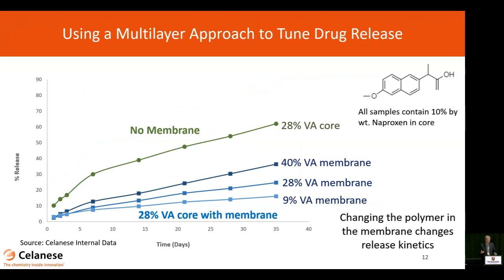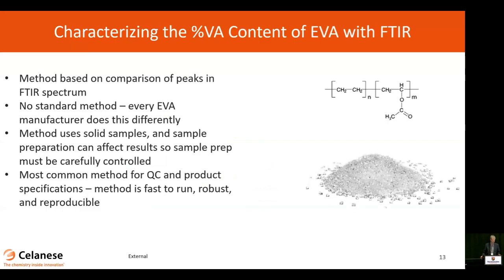Here's just another really simple example that we did in the laboratory with naproxen. Again, an easy to handle drug. It was a kind of project we can give to a summer student who we don't have to train in high potent handling techniques. In this case, if you take a 28% vinyl acetate core that has about 10% naproxen by weight in it, you see the release characteristics of that without a membrane. But as we attach different vinyl acetate copolymer membranes to that core, we get very different release characteristics. So vinyl acetate is going to be a really, really critical parameter for the material.